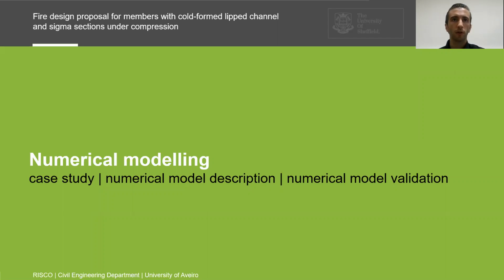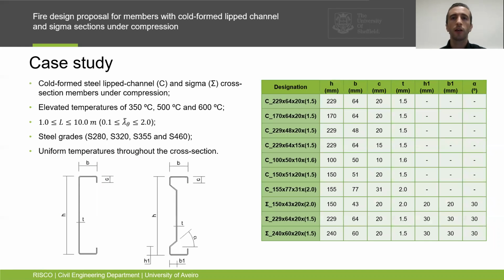Now presenting the numerical modeling, cold-formed steel columns with 10 different cross-sections, 7 lipped channel and 3 sigma sections, under 3 different elevated temperatures were considered. The choice of the temperature, 350 degrees, is related to the recommended critical temperature for profiles with class 4 sections when no calculation is made, the other temperatures being chosen for being common critical temperatures in this type of structural element. Different member lengths were also analyzed, with lengths between 1 and 10 meters, considering this slenderness range, 4 different steel grades, and a uniform temperature was considered.